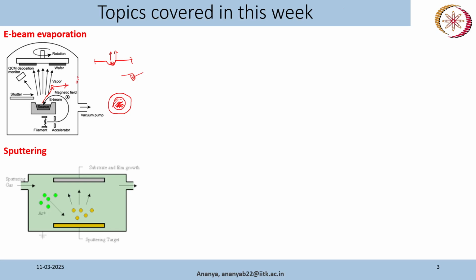Okay, so we do this deposition at low pressure itself, whereas in case of sputtering, when we do the deposition, it is generally at a higher pressure. Initially the pressure will be low, and then we do the deposition at a higher pressure. But in case of evaporation, we try to do it at a lower pressure, so that we get a very uniform deposition, and atoms are moving in a straight line path and depositing only at the wafer. Okay, and so that we can control our thickness very precisely.